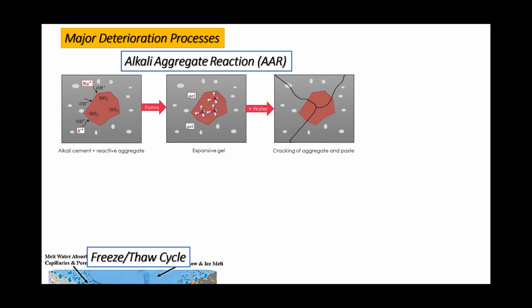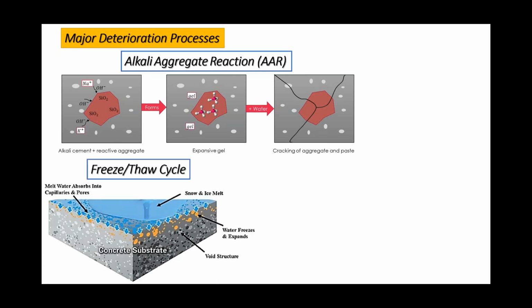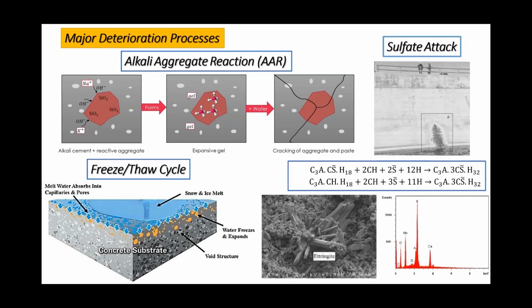Another deterioration process is called the freeze and thaw cycle. As we all probably know, freezing of water inside the pores is going to expand it by 9% in volume, and that water expansion may cause initial cracks inside the concrete, and it affects both the hardened cement paste and the aggregate of the concrete, and it degrades our material.